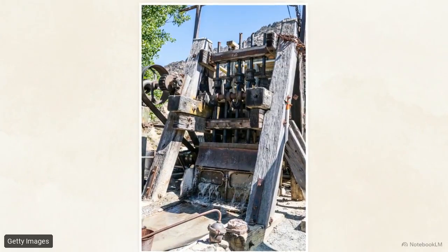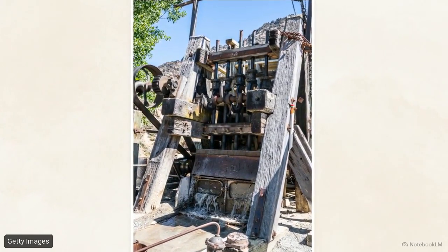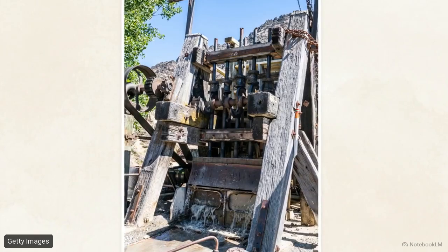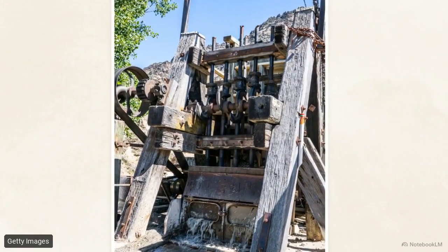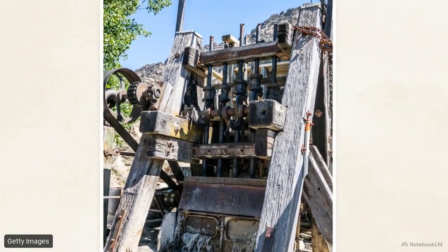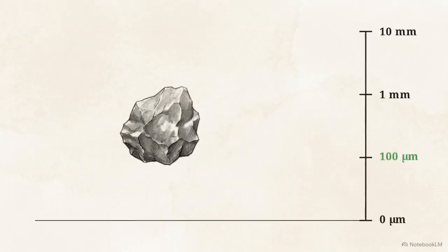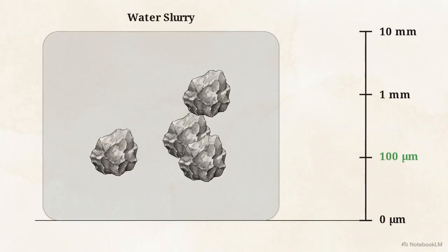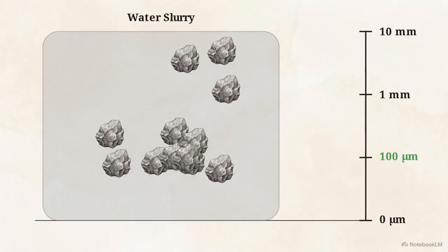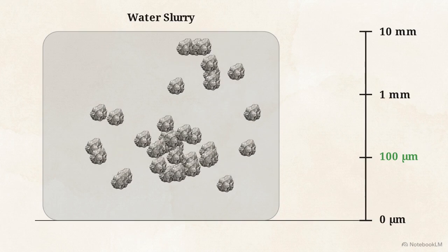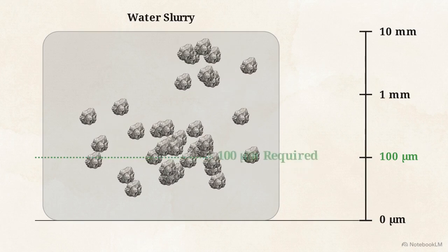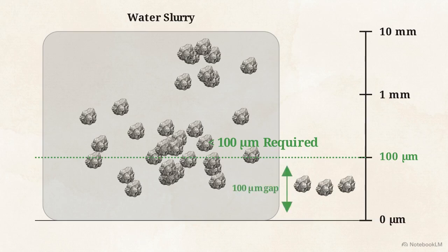Step 1 is mechanical preparation. Operators must heavily crush and grind the raw rock to break it apart and expose the microscopic gold trapped inside. As this scale comparison demonstrates, the ore is mixed with water and ground down into a fine slurry. To expose enough surface area for the chemical extraction, the final rock particles must be smaller than 100 micrometers.